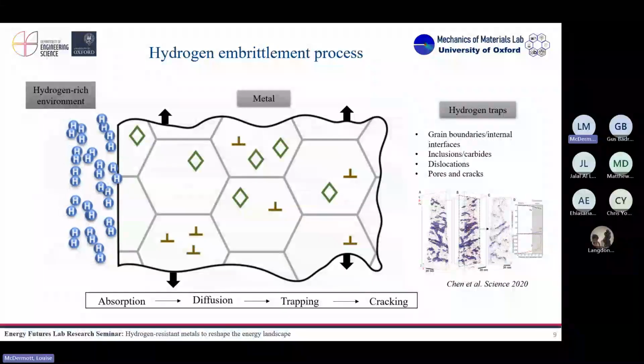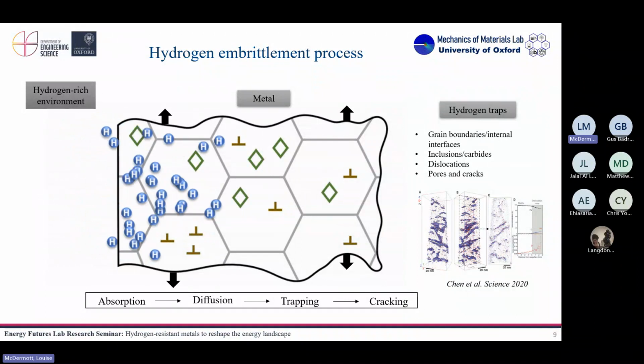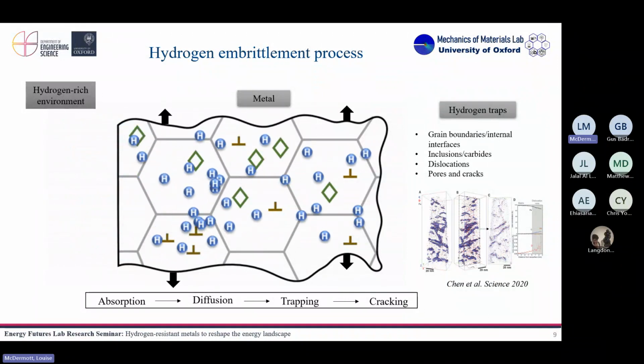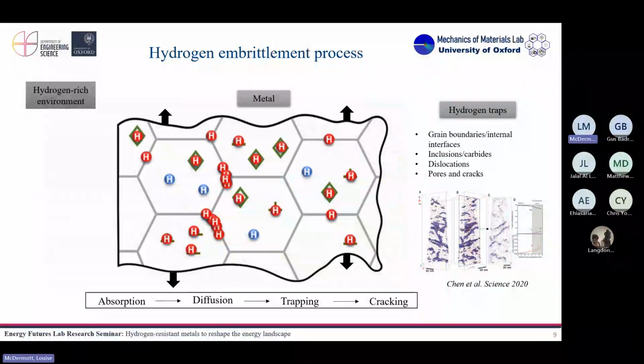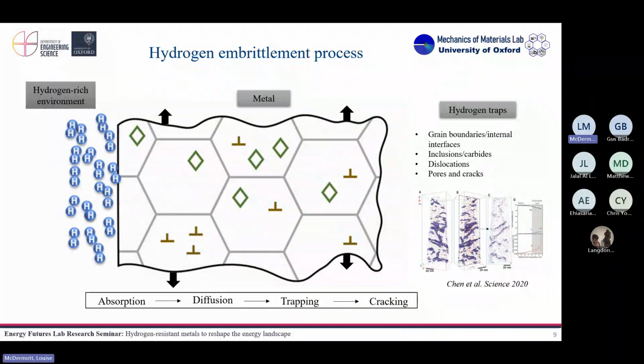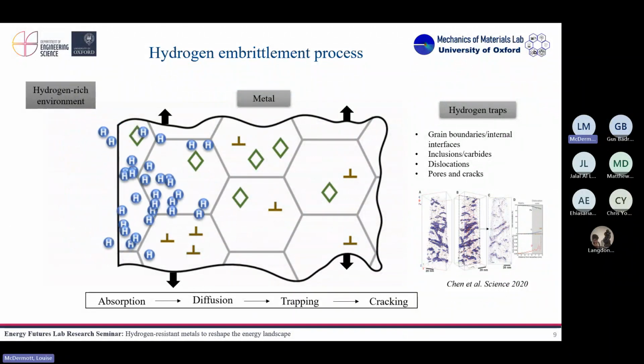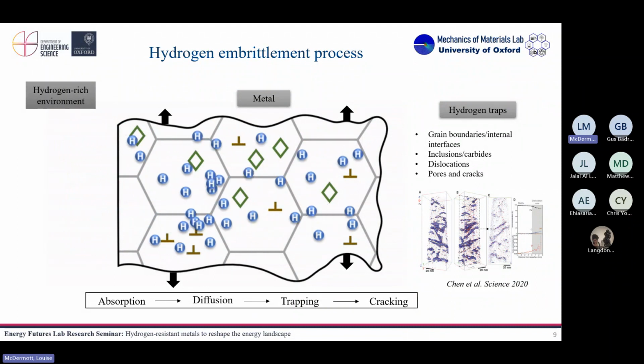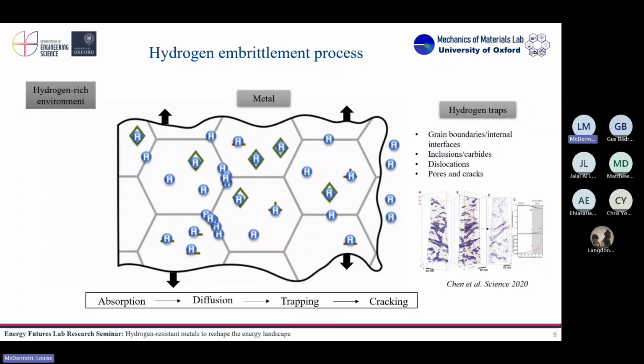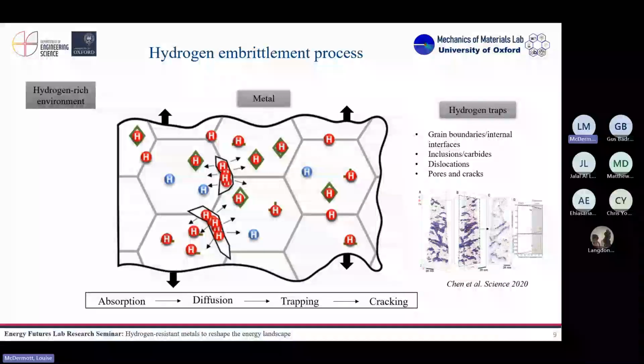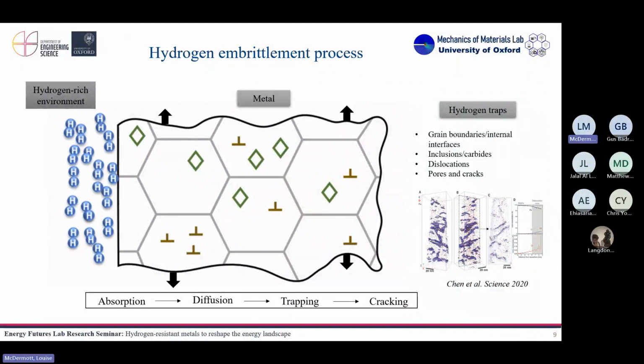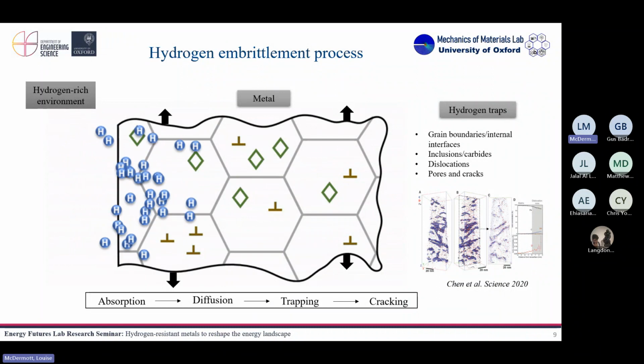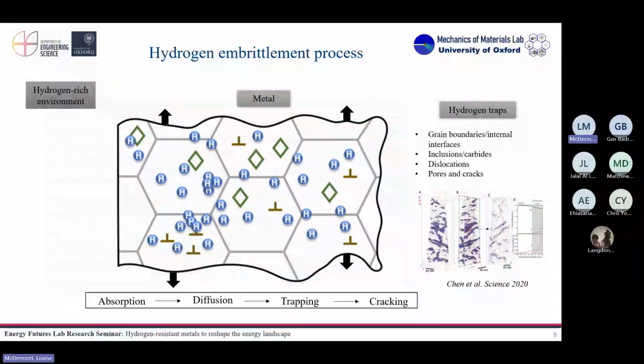And you can imagine that, given that cracks usually start in these defects that tend to accumulate hydrogen, it's very important to characterize them. These are usually called hydrogen traps. There are many methods to characterize how these defects can capture hydrogen, but a very famous one, or the most interesting one right now, is atom probe tomography, that many of you may be aware of. In atom probe, hydrogen is so small and light that we cannot detect it, but we can detect deuterium, which has the same behavior as hydrogen inside the material, because it's an isotope of hydrogen.